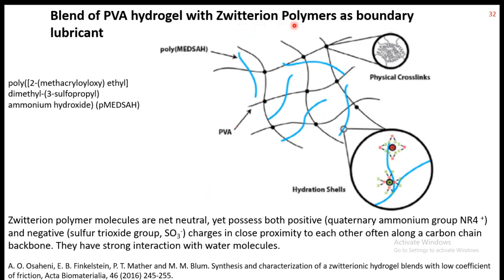So perhaps this kind of polymer molecule will mimic proteoglycan and encourage water lubrication. These zwitterionic polymers can be included within the hydrogel at its surface, so that they provide lubrication, whereas the bulk of the hydrogel provides the mechanical strength to the implant. Perhaps future solutions will be a combination of this kind of hydrogel and zwitterionic polymer, or some other composite with zwitterionic polymers.